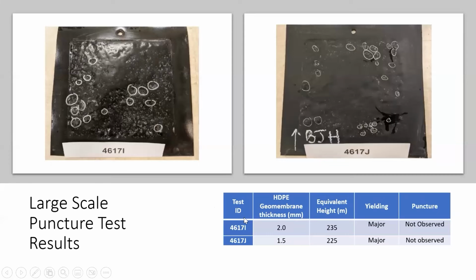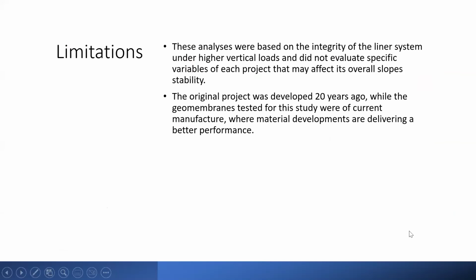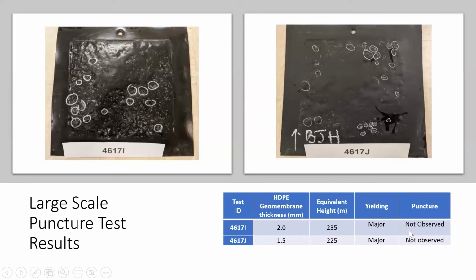And the final stage that we're talking about, more than 200 meters, in this case 235 and 225 for 2 and 1.5 millimeters respectively, major yielding was observed, but no puncture was observed as a result. That was a surprise for us because actually in this test we were looking for the maximum height to try to actually get the puncture failure, and it was not possible. So we ended the test at this time.